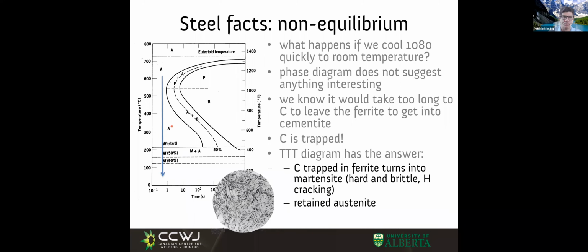So now you know the start time for a transformation and the time to finish a transformation. You know how those times depend on temperature. And you also know that if you cool too fast, you cannot transform by diffusion, and you transform in a way that does not involve diffusion. That is martensite, where the carbon is essentially not moving.